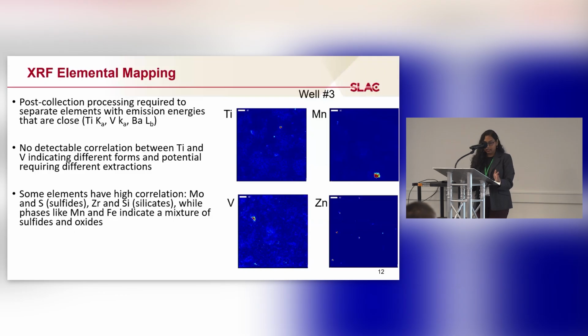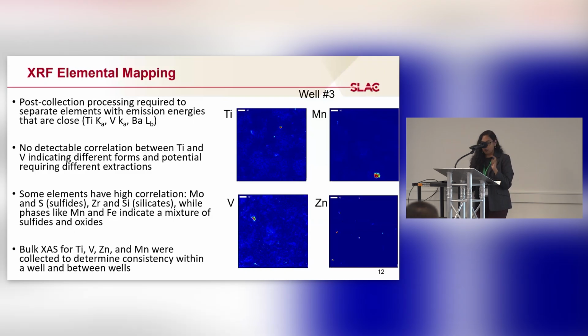And after doing this, I also did X-ray absorption spectroscopy at the synchrotron for titanium, vanadium, zinc, and manganese for understanding the speciation of these materials. The only reason I did only these 4 is due to the limitation of timing. If I had more time on this project, I would have been able to do more. That would have given more information. But this is what we have at this point.